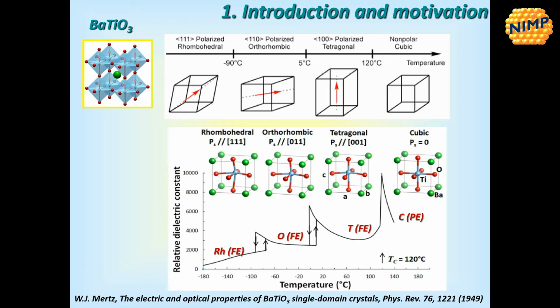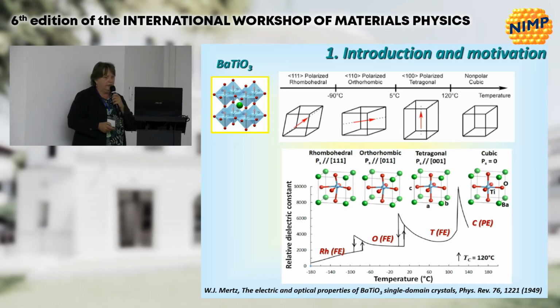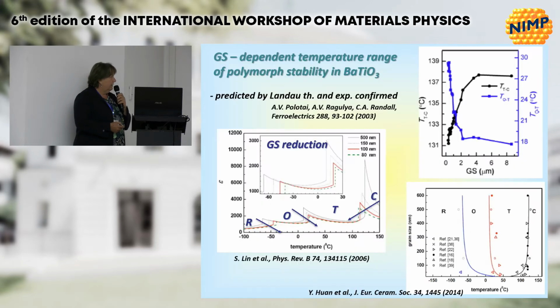All these structural transitions are first order, and the physical properties, like in many cases of phase transitions, are subjected to anomalies, to peaks, to maxima. For example, the permittivity has this kind of jumps. This is the crystal A-axis permittivity, because the permittivity measured along the C-axis, the polar axis, is very low. Practically, in ceramics we have an average due to the random orientation of grains.